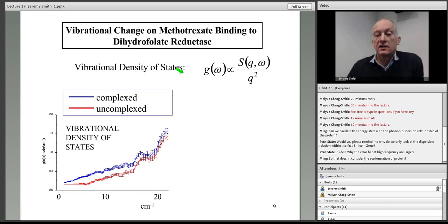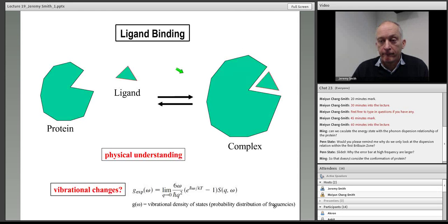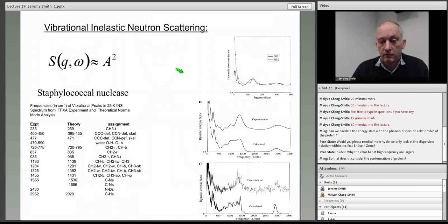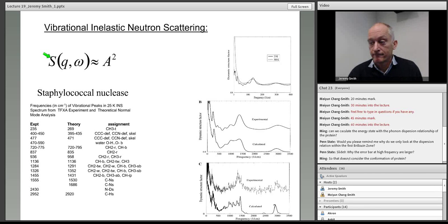That is because of this function. I'll go back here. The measured intensity is proportional to the square of the amplitude. Now the statistics are proportional to the intensity. In other words, the higher the intensity of the peak, the better the statistics you get. Now, one equation that's not on here is that the squared amplitude is proportional to 1 over the squared frequency.